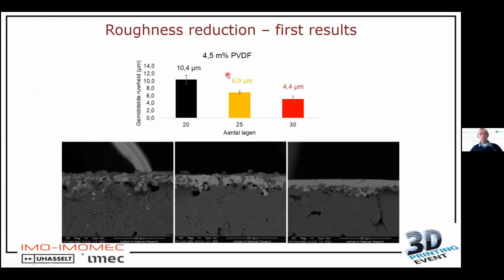Okay, so if we look at the first results, using 4.5 weight percent of PVDF in acetone, this is still in Dutch. Here you see the roughness, here you see the amount of layers, and you see that if you start with 20 layers, the roughness reduces from 20 to 10 micrometers, and putting more and more layers, you go down to 4.4 microns. We did not reach this 2 microns yet. If you look at the cross-section SEM images here, for 20, 25, and 30 layers, you see that for 20 layers and for 25 layers, your PVDF has penetrated a bit inside the top of your 3D printed part, while with 30 layers you see that you already form a coating on top of your 3D printed part. And I can imagine that if you have very stringent limits, this is not what you want.